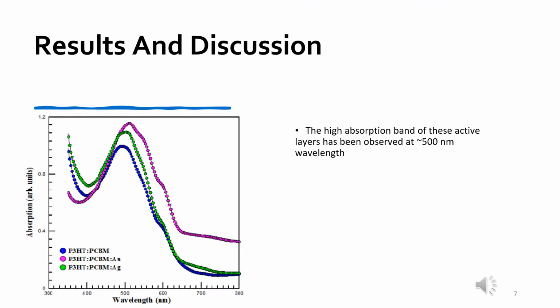The first result we got shows the relation between the light absorption and the wavelength. We can see that the optical absorption increased with the addition of Au and Ag nanoparticles at 500 nanometer wavelength. The increase in absorption could be related to the roughness that may scatter the incoming light, which leads to increasing the path length in the active layer.